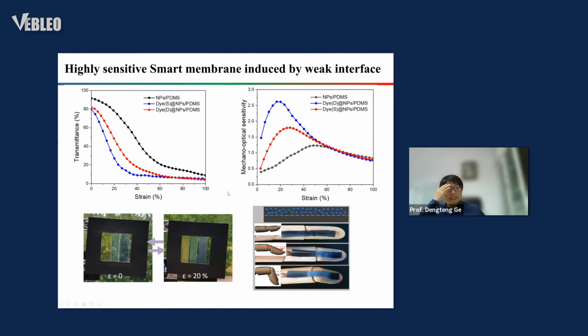When we test the transparency change versus strain, we found that when we introduce the dye, the transparency is lowered a little bit, but the sensitivity is increased very much. So this could be used for a smart membrane, also like a sensor for mechanical deformation.